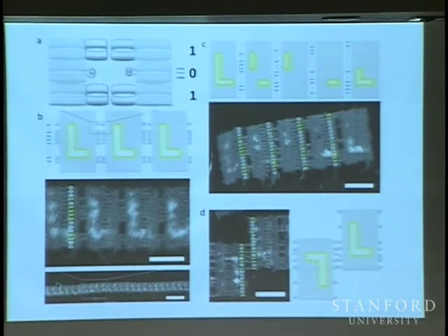But the kind of off-model thing that happens is these cylinders are not perfectly rigid, so your binary code can bend. Here's the staples binding, holding these guys together, and you can see these little ones here have bent to match. So you can try and put that into the sequence finding thing too, to try to find ones that can't bend. That's the kind of thing we can do.